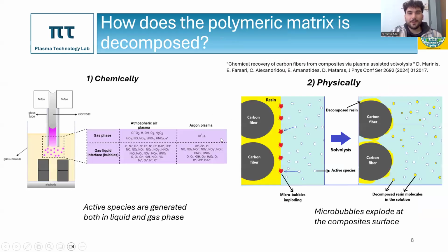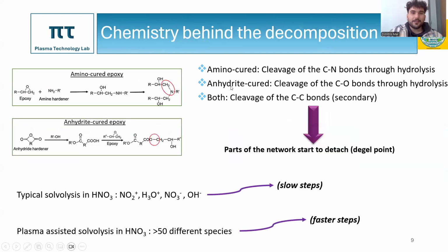But how is the polymeric matrix actually decomposed? Two are the main reasons. First of all, chemically, because as I mentioned, the active species that are generated in both liquid and gas phase basically attack the polymeric matrix and they oxidize it. Also, the polymeric matrix can be decomposed physically too, because microbubbles tend to explode at the composite surface, thus enhancing the degradation even more. But we'll focus mainly on the chemistry behind the decomposition.